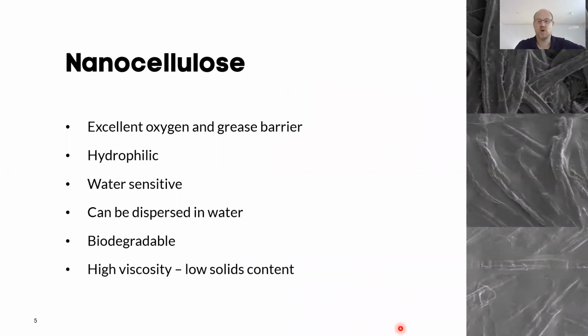Nanocellulose, if we go through them one by one, gives an excellent oxygen and grease barrier. It's quite hydrophilic, very water sensitive too. The advantage there is that you can disperse it in water, which means you can have a water carried system. It's biodegradable. The problem is that you have a very high interaction between the cellulose and the water, and that gives a high viscosity, and you somehow have quite low solids contents here.